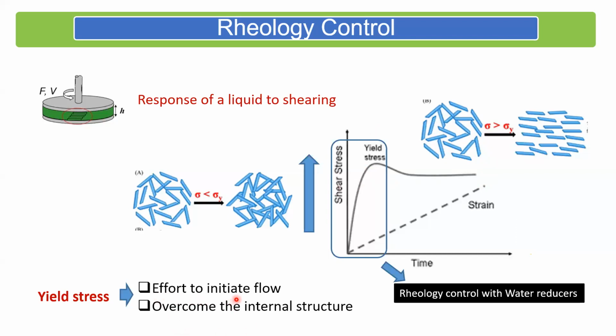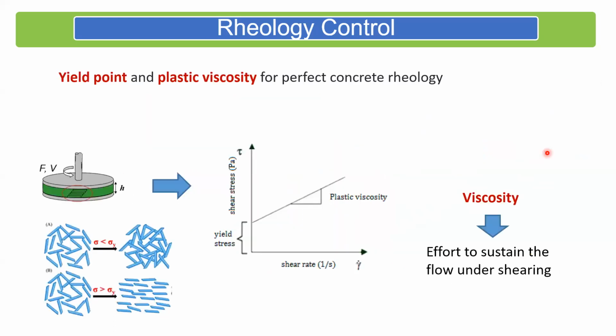So there is this effort which is required to initiate flow. That is the key thing to understand. The higher the effort required to initiate flow, the higher the yield stress. Now, of course, that would come when I overcome the internal structure of the cement inside. What do water reducers do? They basically give me rheology control. What they do is they disrupt the structure. They do not let the structure form. They disperse the cement grains, so cement paste flows very easily. This network is disrupted, so it basically transitions into steady state very quickly. That's what these high-range water reducers, or water reducers, do.